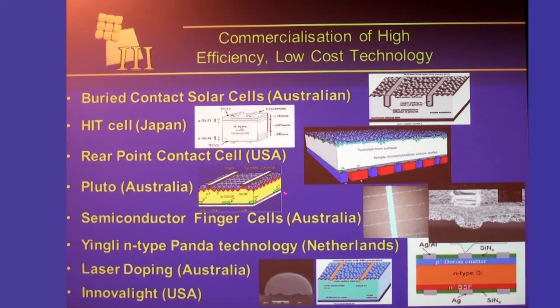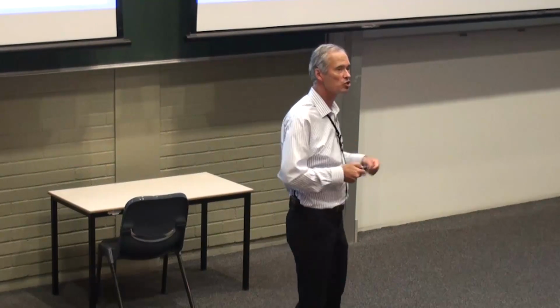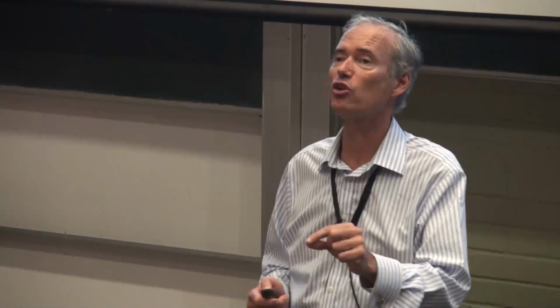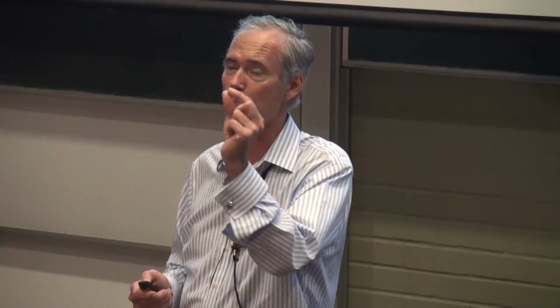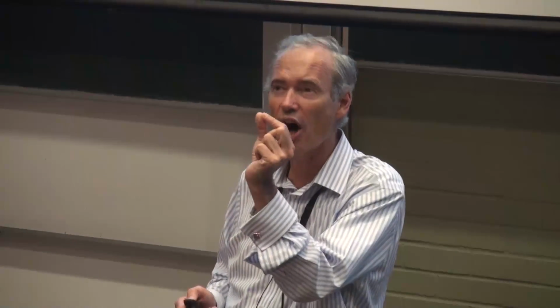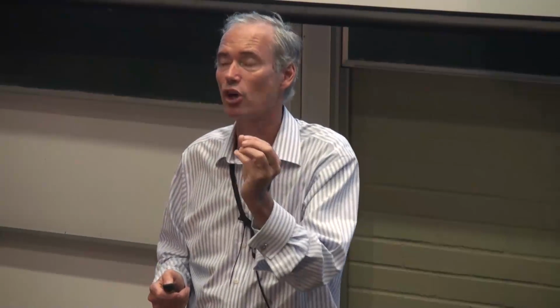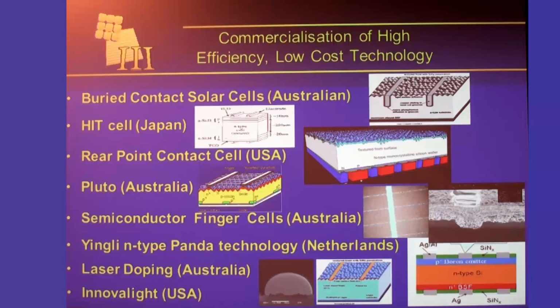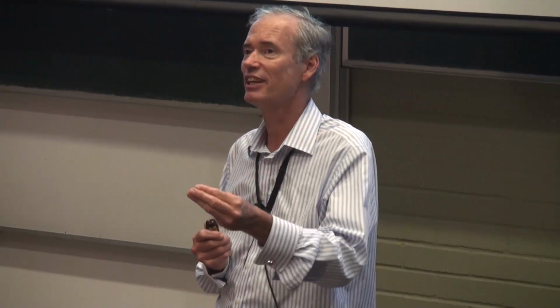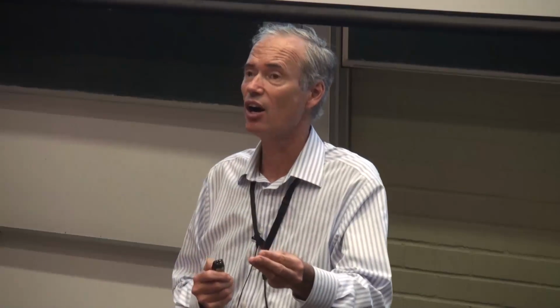So in our labs, for this metal here, we use a titanium, palladium, silver sandwich. Very, very expensive. So we use titanium initially directly onto the silicon because it's a very low work function metal, gives us a very low contact resistance. It means that we can reduce the metal silicon interface down to a really tiny amount, and reduce down the recombination accordingly. And then we want to put silver on top of it because silver is very, very conductive, 1.6 microohm centimetre. So it's the best conductor. So we want to have silver on top of the titanium.